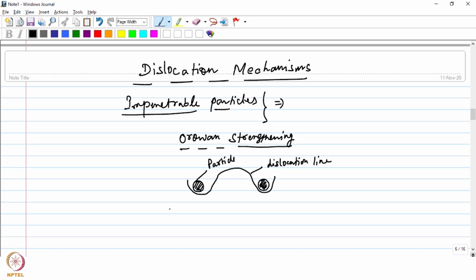And here the strengthening is given by this particular equation, where G is the shear modulus, B is the Burgers vector of the dislocation, and lambda is the spacing between the particles or the interparticle spacing. So from here you can see as the distance between the particles decreases, the strength will increase.